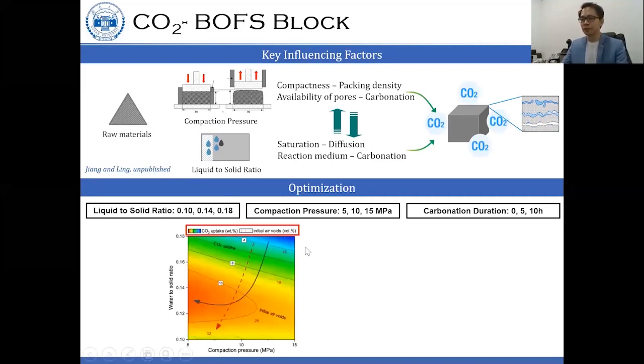So from this figure, as we can see, if we decrease the water to solid ratio and decrease the compaction pressure or molding pressure, we in turn increase the initial air void, 13, 19, 26, represented by the dotted line. And this will also help for the CO2 diffusion. However, at very low water content, it could limit the CO2 reactions. So the best water to solid ratio is around 0.13.